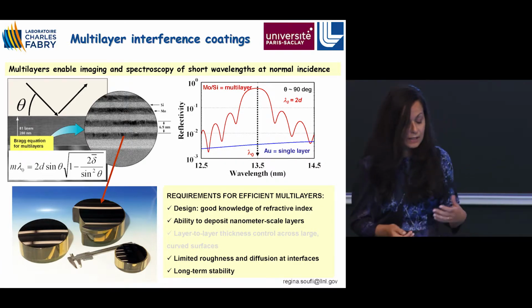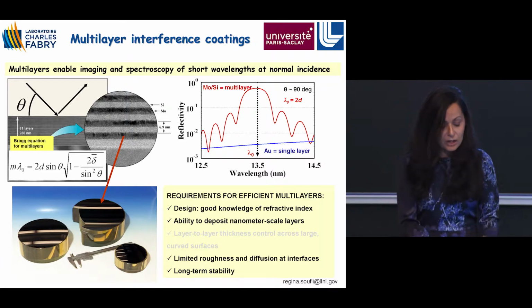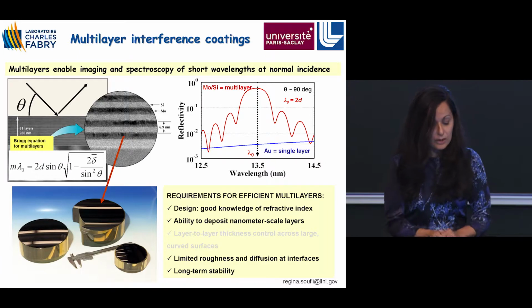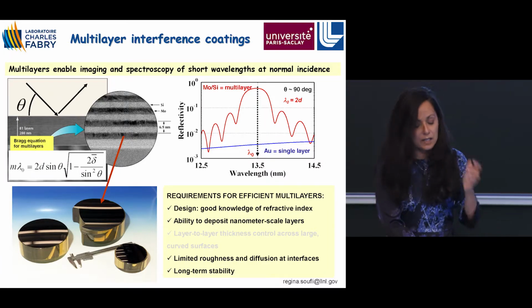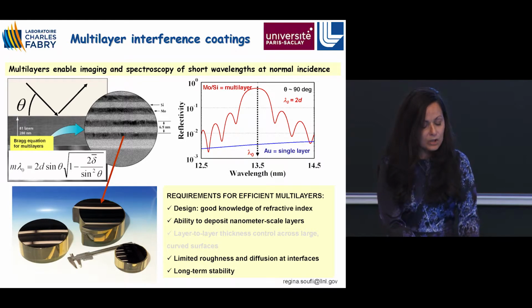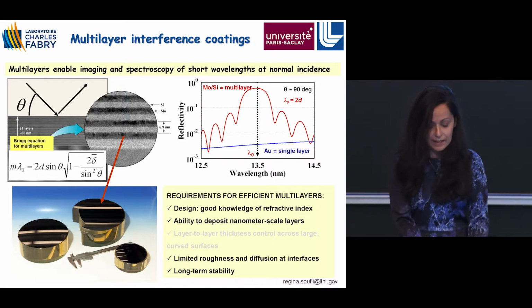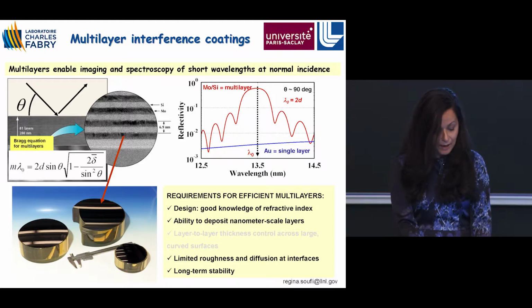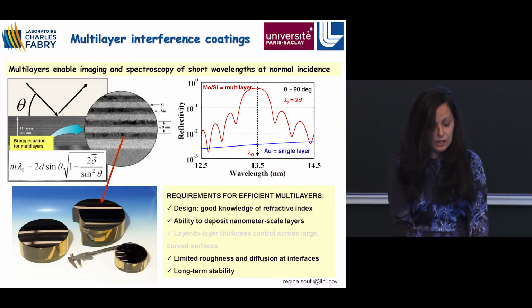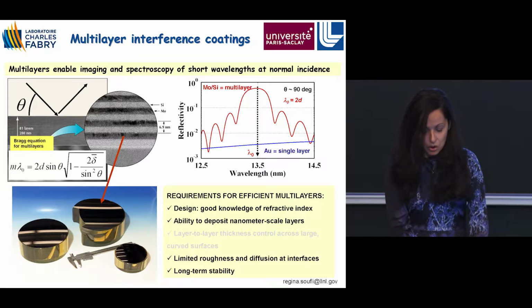So you can think about the structure as a synthetic crystal because it functions according to the Bragg law that we have for crystals. Only in this case, instead of the interatomic distance between the atoms in the crystal, you have the thickness of this bilayer, which we also call the period or d-spacing of the multilayer. The peak wavelength is governed by the Bragg equation. M is the Bragg order; we talk about M equals 1 for most of this presentation. Lambda is the peak wavelength. D, as I mentioned, is the period of this coating. Theta is the angle of incidence from grazing. And this is a factor that represents the refractive index. Delta is part of the refractive index, which is a small correction, basically. So you can see that at normal angle of incidence, where theta is 90 degrees, this thickness needs to be approximately half of the wavelength of operation.